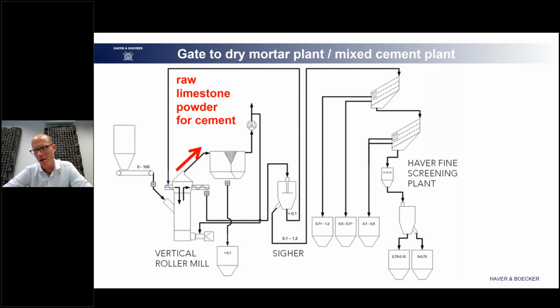And I believe beginning in the 90s, we have a concept here that it is possible to extract from the head of the vertical roller mill the grits, the sandy grits that are not small enough already to leave the head of the vertical roller mill as a powder, and shall not fall down again and be ground again. So we can extract exactly these grits, say 0 to 2 millimeters, and take this material, do a sifting step,